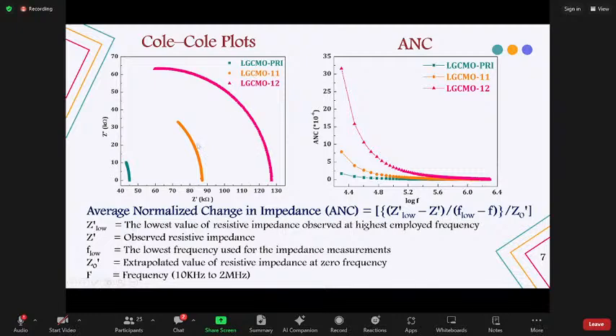These are the Cole-Cole plots and the ANC plots. From the Cole-Cole plots, we can get to know about the role of the grains and grain boundary in the electrical properties. From this graph, we can say that from LGCMO pristine to LGCMO12, we are obtaining a larger semicircle, so there is an effective role of the grain boundary in the electrical properties. And this is the ANC, that is average normalized change in impedance with respect to applied frequency. From this, we can know the key role between the grain boundaries and the grains. From this graph, it is seen that the value of the ANC decreases with respect to applied frequency, which is the characteristic of electrical polarizability of the material.